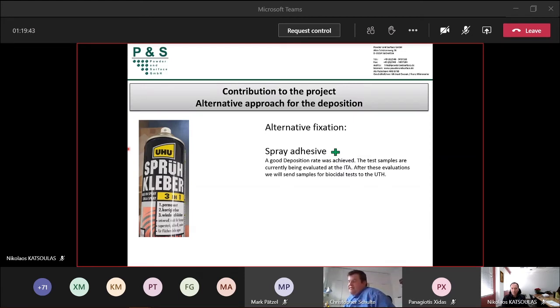Let me say a short sentence regarding coated monofilaments and fabrics. Before we started the project, we were convinced, okay, we will modify the monofilament or the filament and then process this to fabrics. But we forgot a little bit that we established there an abrasive functionality. So we make something like a grinding tool with this monofilament, and then if you work it on your machines, you will kill the machine rather fast. So we shortened this package with monofilament coatings rather strongly, or brought it directly to fabrics. Coating of fabrics was the main work then.